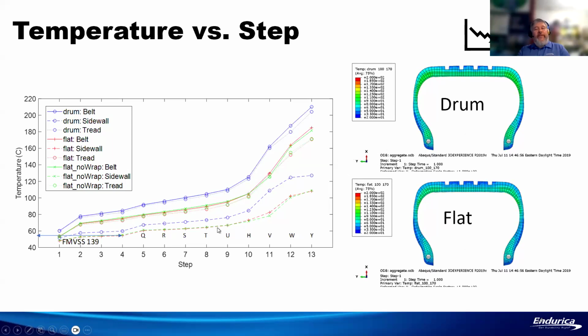Now, of course, when you're just running the structural and the thermal finite element models, we haven't calculated damage yet, so we can sort of calculate a notional stress strain field, a notional temperature field. A tire is never going to reach 200 degrees Celsius because the rubber is going to catch on fire and burn before it hits 200. But if you ignore the fact that material can fail, then the stress strain and temperature fields will give you this information. And now we need to use the damage tolerant approach to accumulate the damage and find out in which of these steps the conditions are so severe that the tire is done.